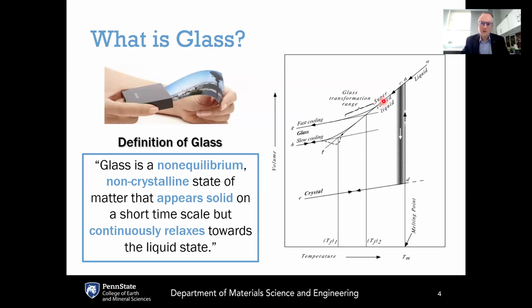Now, if we take this supercooled liquid and we continue to cool it, what is happening is that the viscosity of the supercooled liquid is becoming higher and higher. And it's not just increasing by a little bit, it is increasing by orders of magnitude, meaning that the supercooled liquid is becoming less and less fluid. It's taking more and more time for the atoms in the supercooled liquid to flow, and they're getting a lot more sluggish in how they can move around.